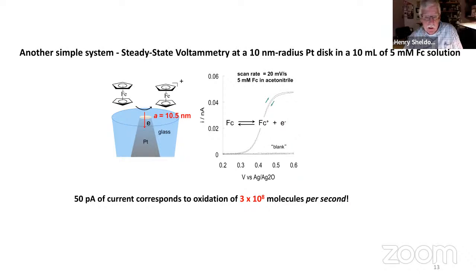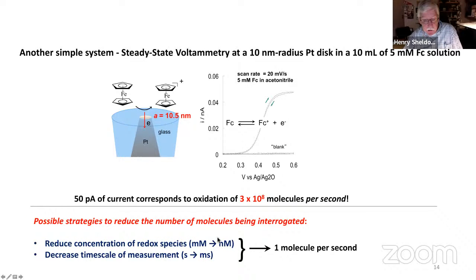And you say, wow, that's a really small electrode. That's still a lot of molecules. How do I get down to single molecule events in this experiment? And you can think about strategies. There are different strategies. You can reduce the concentration of redox species from, this is a 5 millimolar ferrocene solution, you could go to nanomolar. And that reduces this event rate by a factor of 1,000,000. And then you could decrease the time scale of the measurement. This is a very slow voltammogram. You could go from seconds to milliseconds. You easily get down to a molecule per second arriving at the electrode surface.